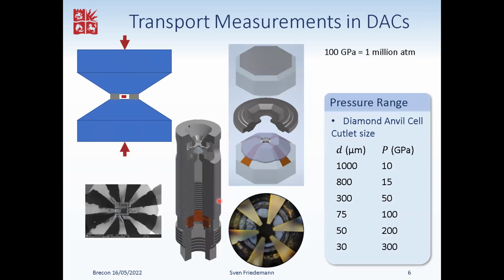So this is a design of the diamond anvil cells that we use. It is 14 millimeters in diameter and about 3-4 millimeters high. A lot of the construction is about making sure that the diamonds are well supported without any chance for them to tilt relative to each other or shift relative to each other, because if the culets don't meet each other, then the diamonds will end up crushing each other. So it's surprisingly easy how you can actually chip two diamonds by having them touch each other on some edges. One has to be quite careful that one never does this also in the preparation steps.